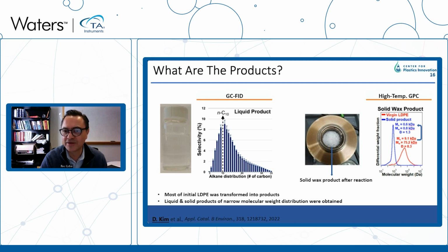And what I show here is the result of high temperature GPC measurement in which we compare the molecular weight distribution of the virgin low density polyethylene that we use in this process with the product that we're obtaining that has much lower molecular weight. So these are species that have about 80 carbons or so in them. You can see from this graph that essentially all the polyethylene that we feed into the reactor has been processed or has reacted and has been reducing molecular weight by a factor of at least 100.